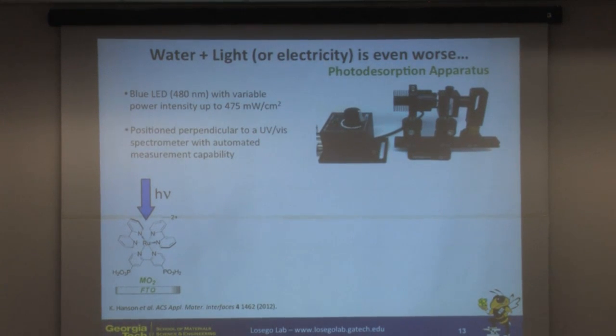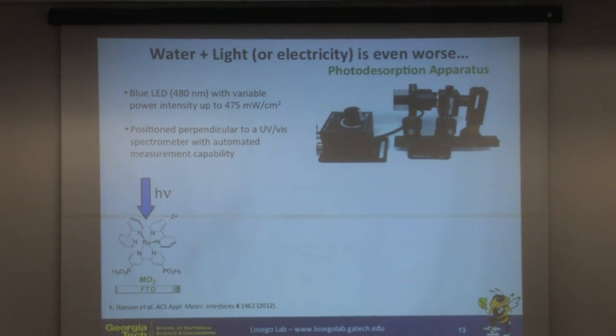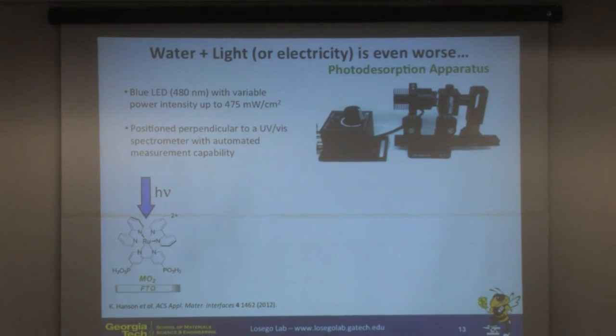So if we want to put this into a real device where we either want to run current through the device or we want to expose it to light, to absorb light, for example, for a solar cell, well, this causes even more detachment. All right, so this was a study done by my colleague Ken Hanson prior to us collaborating, where he was looking at these dye molecules, phosphonic acid bound to an oxide substrate, and he looked at their detachment as he was exposing them to blue light. And so not only were we in now some aqueous environment, but we were also exposing them to light.